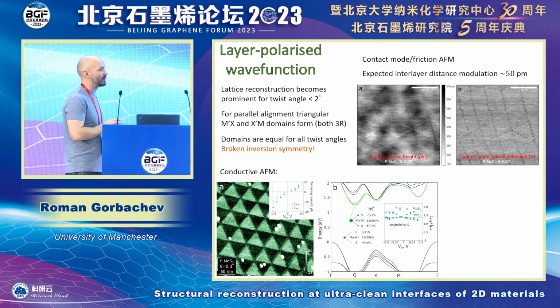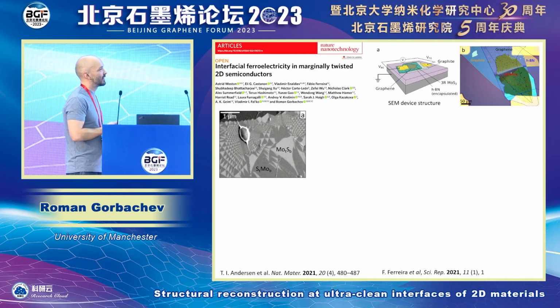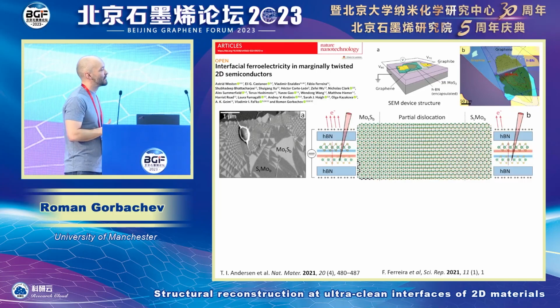because these are the states you would normally tunnel to from the conductive tip in AFM with a specific metal. So that is kind of a quick illustration, but if you go a little bit deeper into this, it turns out that this is not just a single wave function being asymmetric, it's entire electron density being asymmetric. And in fact, if you plot this and calculate DFT for the electron density, you will see that there is, in between the layers, a charged capacitor, which is electron density and a hole density accumulated due to the symmetry, due to hybridization of the conduction and valence band. And this is ferroelectricity in principle because you now have electric polarization, which is pointing up for this configuration and pointing down for the opposite configuration.